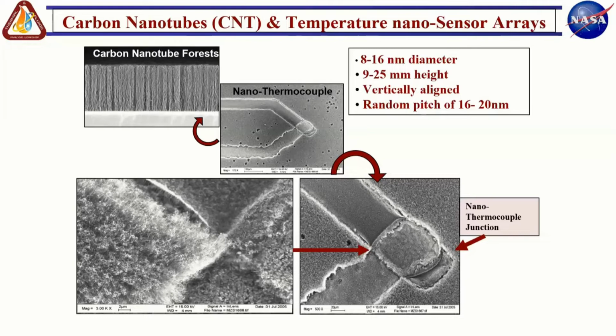And then right next to these nano thermocouples, we were able to put a nano coating of carbon nanotubes. And typically these were about 8 to 16 nanometers in diameter. I notice I have a printing mistake here on the slide. They were about 9 to 25 micrometers in height. And I apologize, it's showing up as millimeters, but it's actually micrometers. So about somewhere between 10 and 25 microns in height.